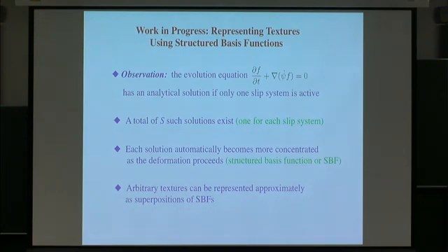It's not like, for example, spherical harmonics, generalized spherical harmonics, in which you need more and more of them as your texture gets sharper. In this case, you can imagine representing arbitrarily sharp textures using just a handful of these structured basis functions, equal in number to the number of slip systems.